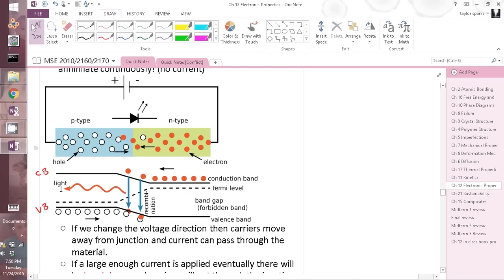This gives off light. And then even better, we can change the color of light that it gives off, because we know that energy is not destroyed. Therefore, if this is the band gap, and it's equal to, let's say, something like 3 electron volts, what color of light should that give us? We can calculate it. We would say hc over lambda, right?